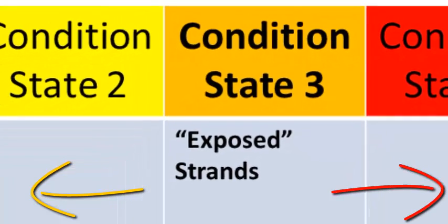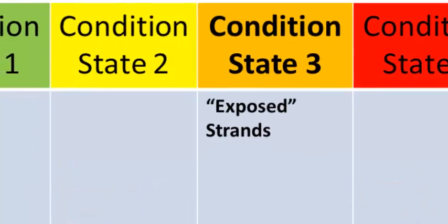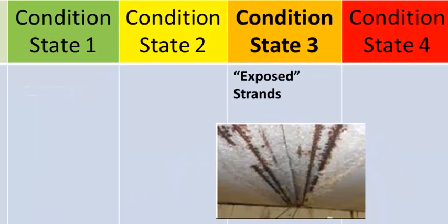So the first one we'll talk about is the exposed strands, and this is pretty common once the moisture starts wicking through and getting between the adjacent boxes through the shear keys, and the corrosive process can then begin with that chloride. And this image is a photo taken down the keyway on the underside of the pre-stressed box beam bridge, and there's 2 beams here, one on the left, one on the right, and each of these beams have exposed strands.